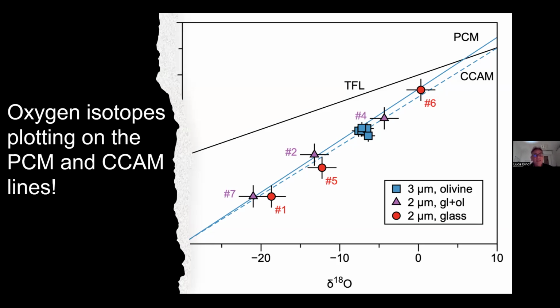And what is very important is most of the materials have been characterized by NanoSIMS at Caltech, but you will see that all other samples, just in this case, for example, were collected in different laboratories. For example, this came from the University of Wisconsin in the United States, or you have recently characterized the oxygen isotopes of the Italian materials in France, and all the data plot exactly on the same line and very, very close to each other. So it is actually impressive.